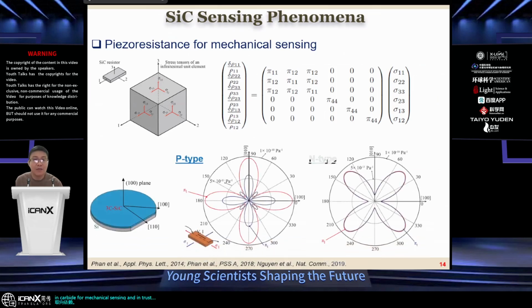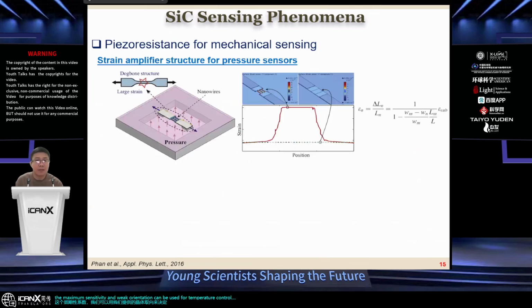And interestingly, we found that silicon carbide exhibits orientation dependent properties. For example, for p-type silicon carbide doped using aluminum, the piezoresistive effect will be maximum along the 010 or 100 direction. On the other hand, for n-type silicon carbide doped with nitrogen, we will have the maximum sensitivity along the 110 orientation. Meaning, based on these piezoresistive coefficients, we can decide which crystal orientation offers the maximum sensitivity, and which orientation can be used for temperature compensation circuits. And we also develop some smart mechanical structures to further enhance the sensitivity of devices using the silicon carbide piezoresistive effect.